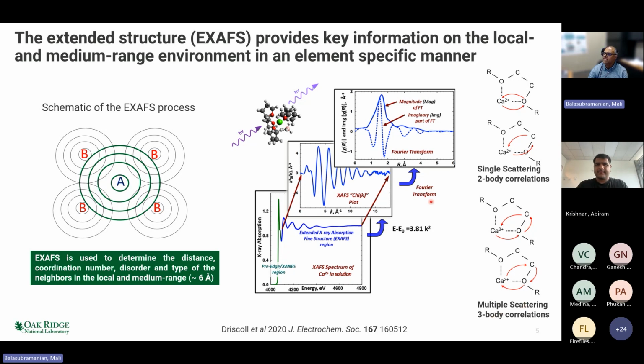And so the EXAFS encodes all information from both single scattering and multiple scattering. And with appropriate analysis, in many cases, you can invert back these signals and model the local structure to about 6 angstrom from the central atom. So that is the fundamental basis by which EXAFS is performed.